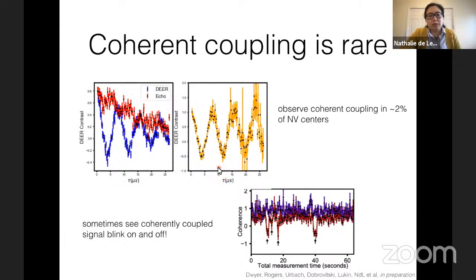And then the final puzzle, that maybe gives you some sense of what might resolve all of these puzzles, is that we found that coherent coupling was extremely rare. So I already told you that these NV centers on average are actually much closer to the surface spins than they are to each other. So you would expect to see coherent coupling in almost all of your NV centers. But instead, we would see this in something like a couple percent of all of the NV centers we looked at. And then occasionally you could even see that this coherently coupled signal would blink on and off on human timescales.